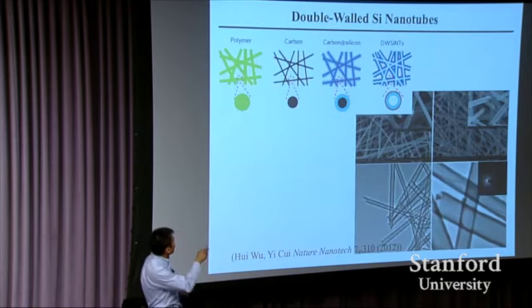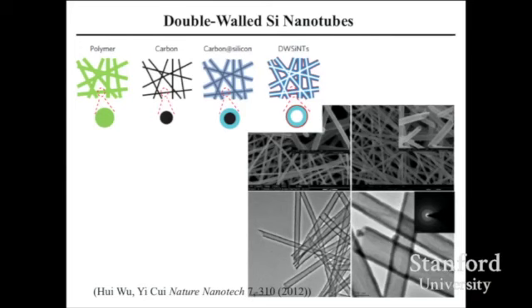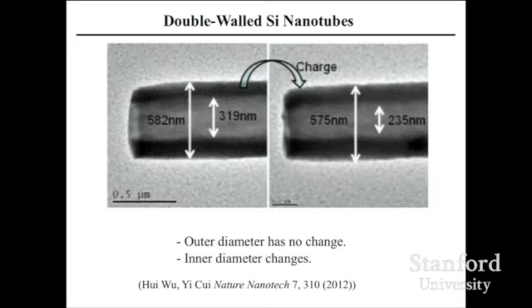And we started to make this double wall silicon nanotube. Go through a process, I don't need to go into the detail. Eventually what we made is silicon inside, silicon dioxide outside. These are the hollow double wall nanotubes you see. So this is really, really beautiful. You look at this. You put lithium in, the outer diameter is almost the same. But the inner diameter now shrinks. Really confirming expansion can go towards inside.